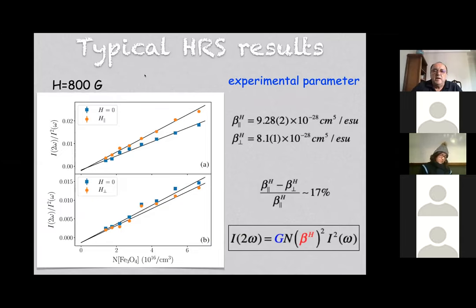Well, for the beta H now, as you remember, we have the second order intensity proportional to the square of the first order intensity and the number of particles or number of molecules that we have as absorbers in the sample. So these are straight lines, even without the magnetic field here, with the magnetic field H parallel to the electric field E, and here perpendicular. So we see that this anisotropy increases with the number of particles we have there, and this angular coefficient also is different from the direction parallel to the magnetic field, and here perpendicular. And this anisotropy is of the order of 17%.